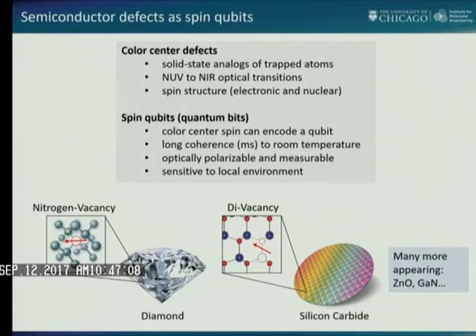But because you can trap the electron, as I just showed you, the spin of that electron is a quantum state that can be controlled. That means you have a prototype quantum bit, one electron whose quantum state can either be sensitive to or be shielded from the environment. So it turns out these materials have very long coherence times of one electron, meaning this superposition of up and down can last for surprisingly long periods, orders of magnitude longer than people thought. You can optically control them. You can optically measure them.